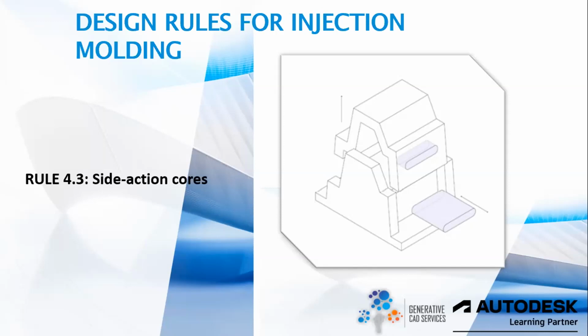Because of this, we advise that you use this when the two above solutions are not viable or don't give you what you want. Then cores can be used that slide out of the part from the side before it is ejected. Side action cores should be used sparingly as they add complexity and increase the overall cost of the mold. It can increase the overall cost of the mold by 15 to 30%, so be mindful not to just use it first.